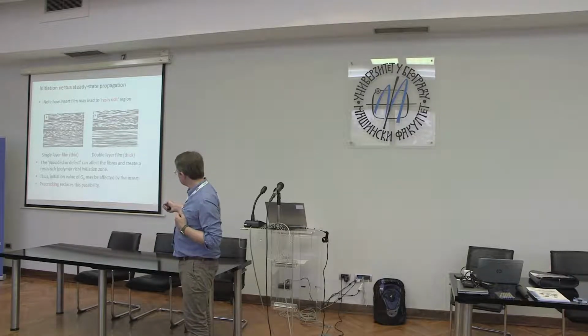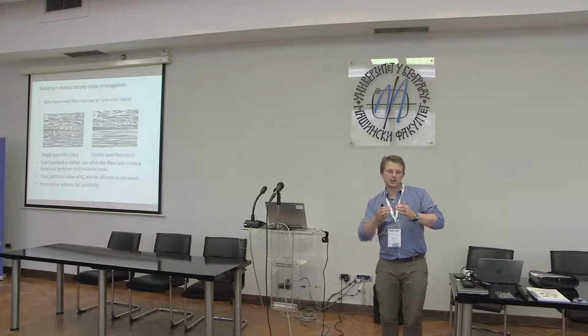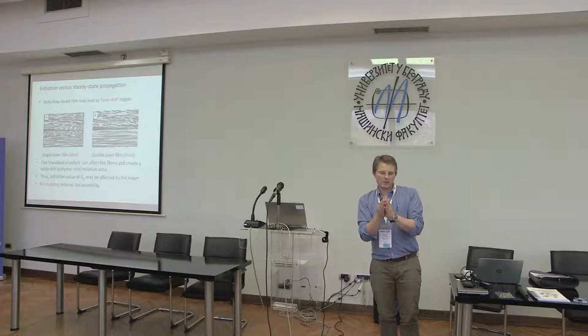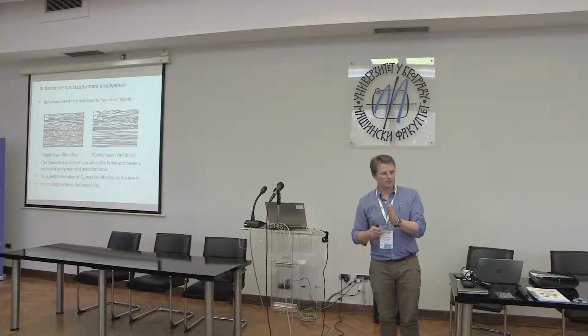So here you can see the tip here is distinctly thinner than the tip around about here. So the embedded polymer film, by being thicker, has created this block of polymer around the crack tip. So the thinner you make that film, the less matrix you're going to have around the end of the crack. Okay, sorry for that not being too clear.